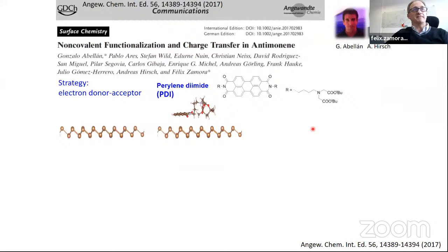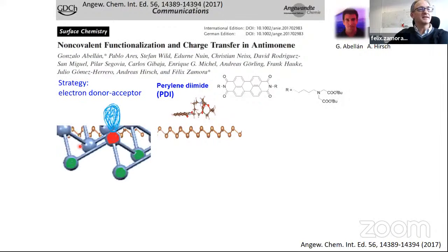Once we were able to obtain the material, we decided to try to do some chemistry. As I showed before, in these layers of antimony we have something that we can use for the chemical functionalization of this material. Every single atom is connected to 3 neighbors, 3 antimony atoms, but every single atom has what I try to represent here, a lone pair of electrons. So the layer should be an electron donor.